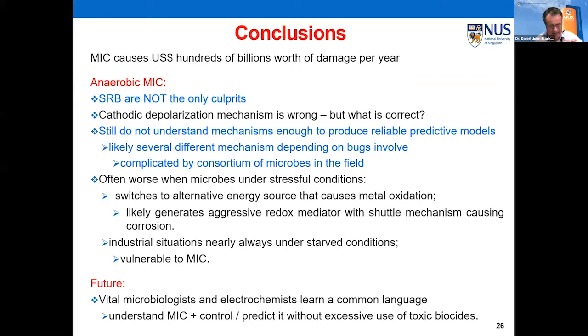There's always this idea that we like to hunt for a single mechanism, but it's probably going to be that different bacteria cause different mechanisms. And it's always going to be complicated by consortia of microbes in the field. It's worse when the microbes are under stressful conditions. They seem to switch to an alternative energy source that causes metal oxidation. I'm fairly certain that they are producing some redox mediator that is more corrosive and accelerates the corrosion. We even have some idea that in deep sea it could be sulfur being produced. The sulfur is corrosive. Unfortunately, industrial situations are nearly always under starved conditions, which is probably why corrosion rates in the field are always so much worse than the ones we have in the lab.